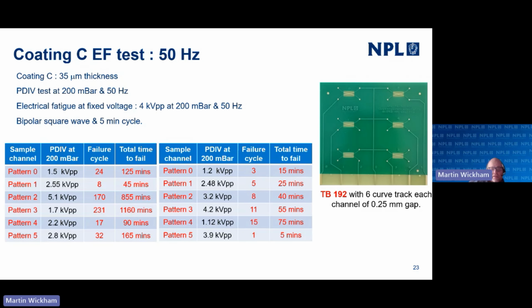This is a different coating. This is coating C. With this coating we're working at 50 Hertz because we were concerned that at a kilohertz we were creating a corona discharge across the surface, which would give us early failures. This is a 35 micron thick coating. Everything else is the same: 200 millibar, 50 hertz, 4 kV peak-to-peak, and a 5-minute cycle time.